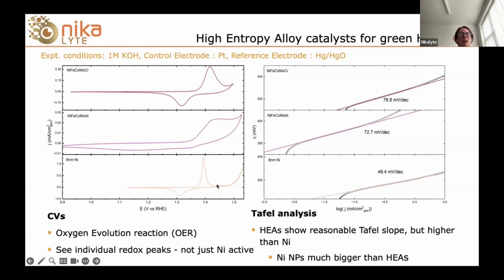So that's encouraging. We then also looked at the Tafel slope of these particular reactions to compare the performance of, again, the same three different materials, the chromium alloy, the aluminium alloy, and then the nickel. And in this case, we did see slightly higher Tafel slopes for the high entropy alloys compared to the nickel. But what should be noted is there are differences in size here between the nanoparticles. So it's not clear whether the size of the nanoparticles, which in the case of nickel are 8 nanometers, and in the case of the alloys were more like 4 or 5 nanometers, whether that is a dominant feature in the differences in the performance.